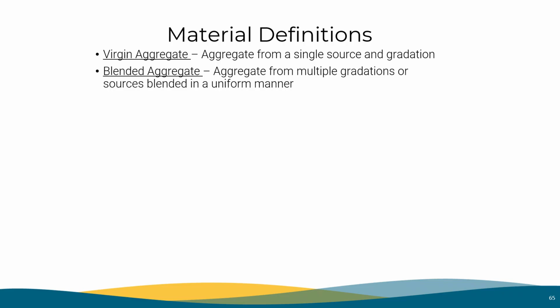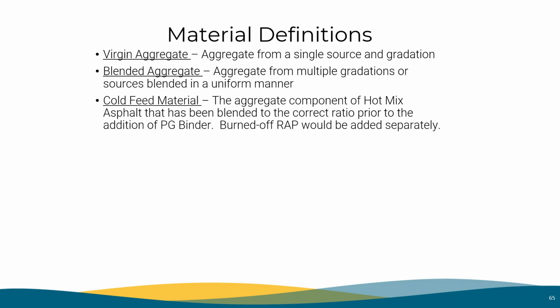Before we begin, let's go over some material definitions. Virgin aggregate is aggregate from a single source and gradation. Blended aggregate is aggregate from multiple gradations or sources, blended in a uniform manner. Cold feed material is the aggregate component of hot mix asphalt that has been blended to the correct ratio prior to the addition of PG binder. Burned off RAP will be added separately. RAP is recycled asphaltic pavement.